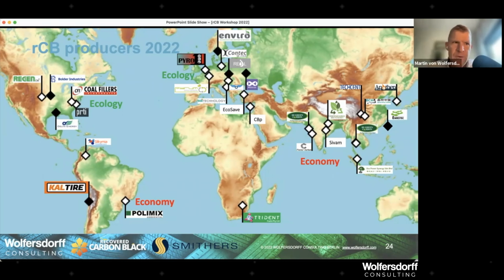Certainly, I will come to the point showing you why we called the workshop to the rescue, because in addition to sustainability attributes, carbon black should also help in places where furnace carbon black is short and not available. Of course, at the moment, the available recovered carbon black capacity is still faint. And so there's a number of considerations: feedstock type, feedstock availability, so how much control you have on the end-of-life tire feedstock, and of course transport. That's like an iteration, because you don't want a long transport for the tires, but you don't want a long transport for your products either. And then the question is, which products are easy to transport, which products might not be easy to transport. I get back to that in the third section in the synergies, if that is all right with you.